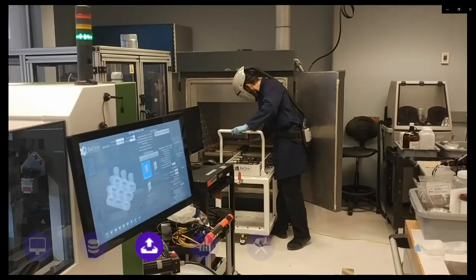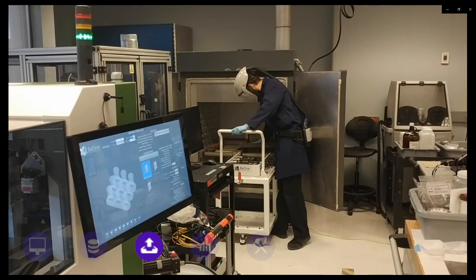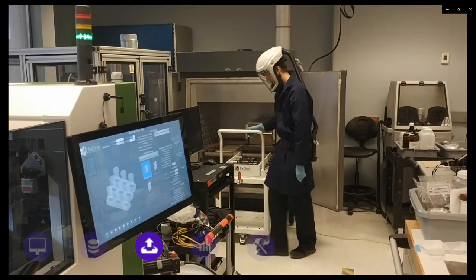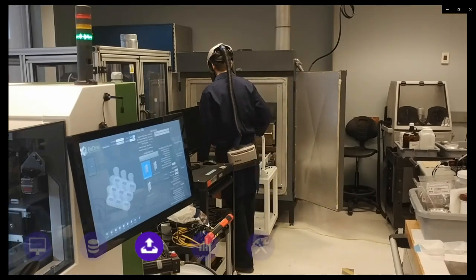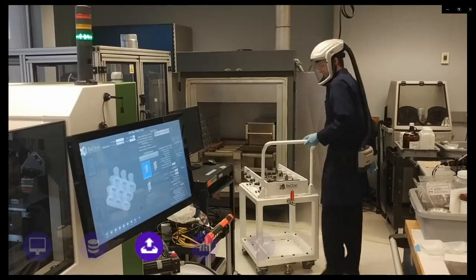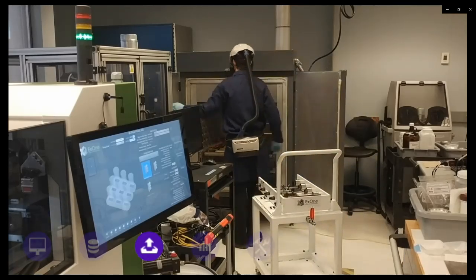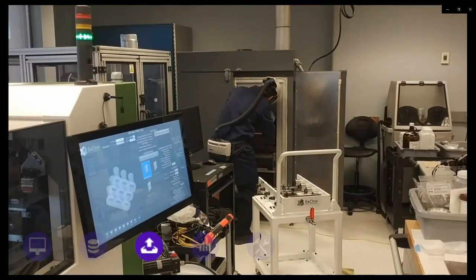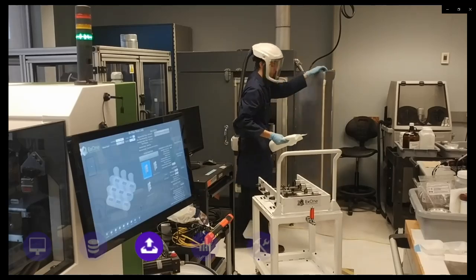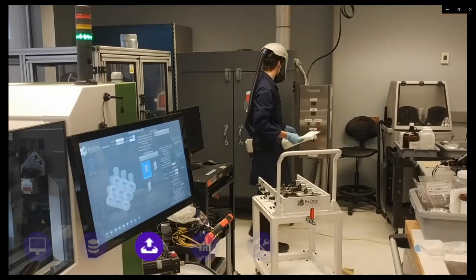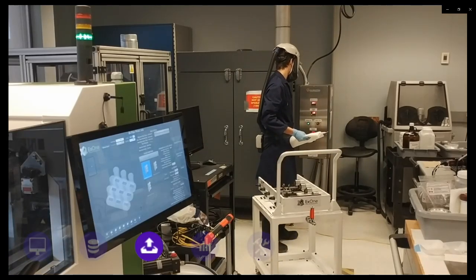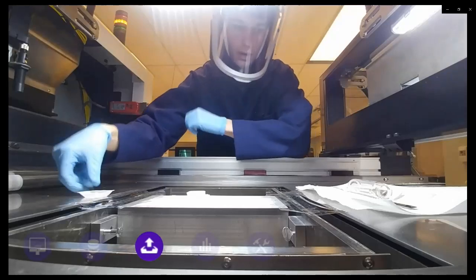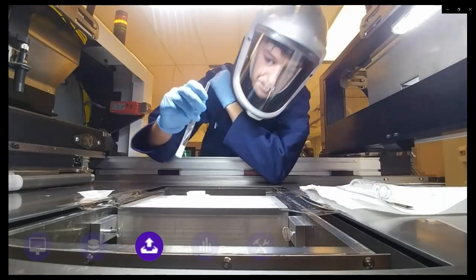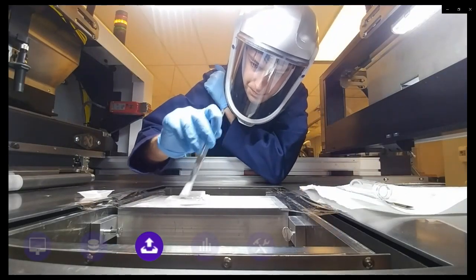There are multiple steps to part heat treatments. The first step is binder curing. Here, we see parts going into the curing oven to finish hardening the binder or glue and allow for the part to be strong enough to be handled during depowdering. The parts can be placed back in the machine after curing to depowder. Once the parts are strong enough to be handled, they are depowdered and cleaned.